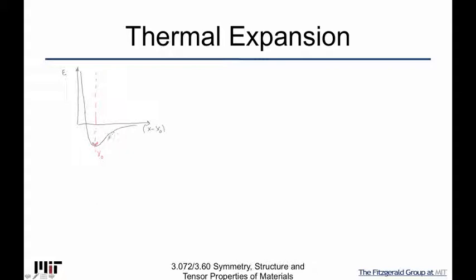this Coulombic force, which deals with 1 over the radius, and then this repulsion force, which is tricky because it's really the Pauli exclusion principle, because you're trying to force electrons into the same small volume, but they can't. They have to have different quantum numbers.